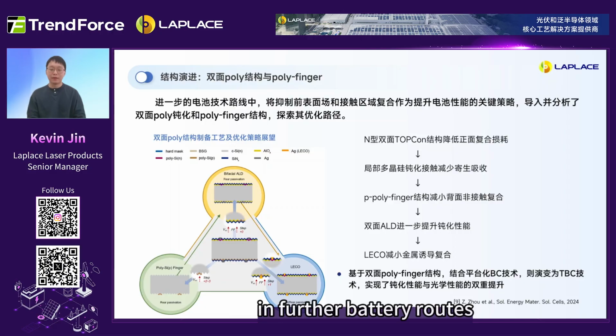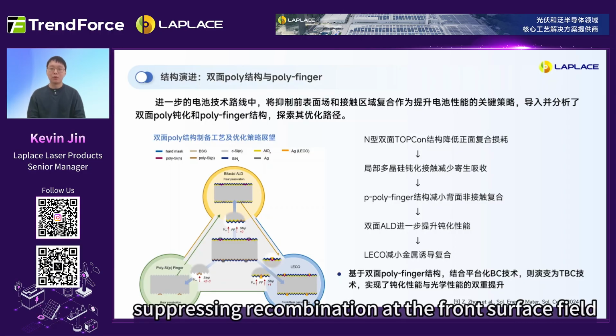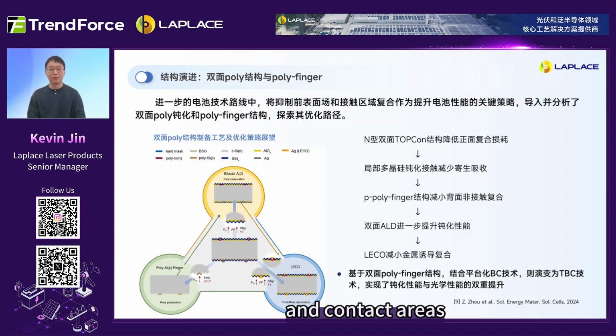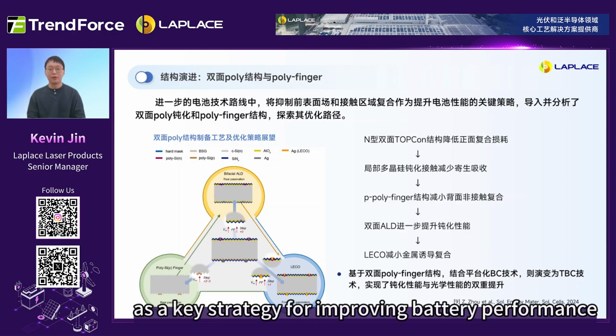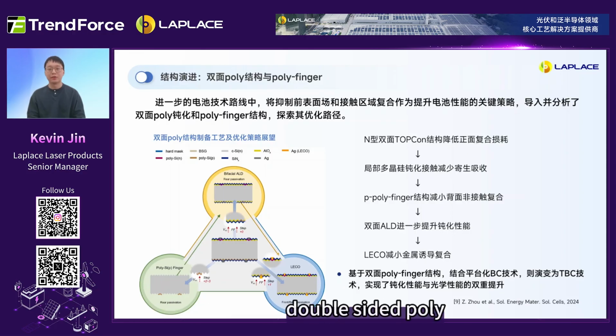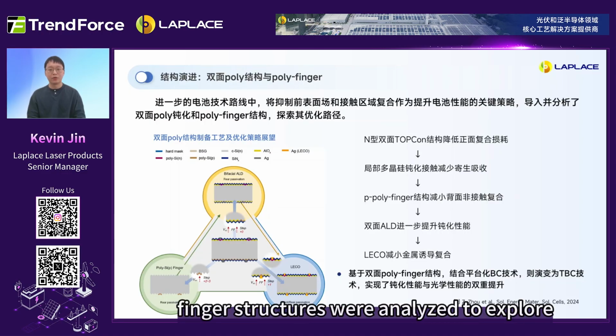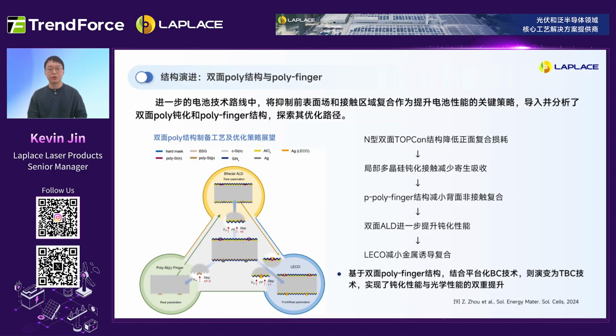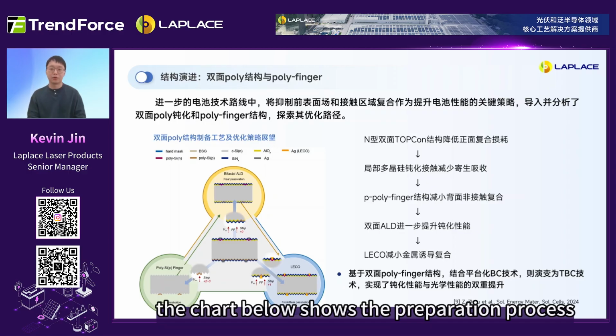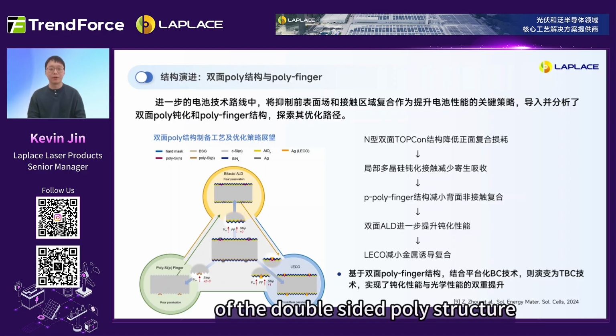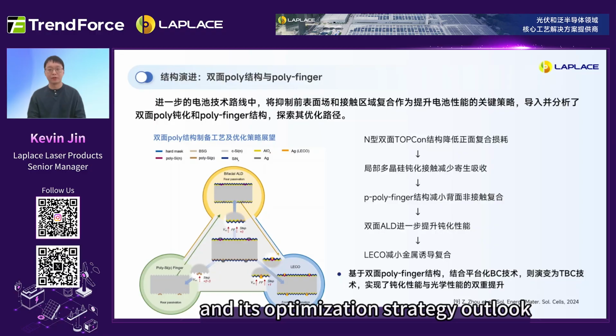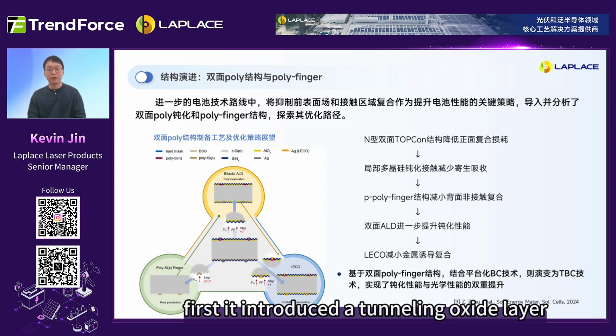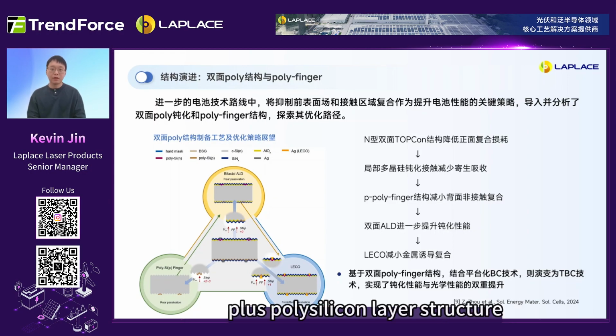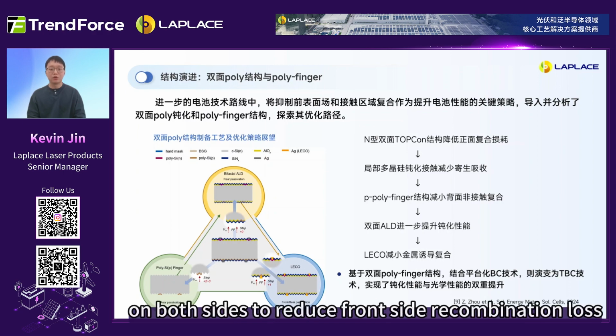In further battery routes, suppressing recombination at the front surface field and contact areas was introduced as a key strategy for improving battery performance. Double-sided poly passivation and polyfinger structures were analyzed to explore optimization paths. The chart below shows the preparation process of the double-sided poly structure and its optimization strategy outlook. First, it introduced a tunneling oxide layer plus polysilicon layer structure on both sides to reduce front-side recombination loss.